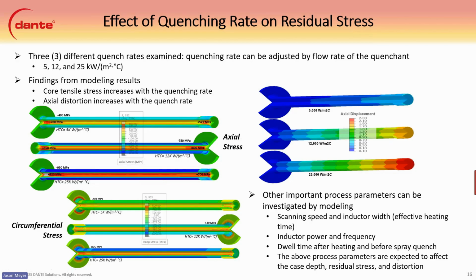Other important processes that can be investigated that we didn't do for this study were the scanning speed of the inductor and the inductor width. So effective heating time, so the larger heating region or the speed at which the inductor moves. The power and frequency, so that the temperature can get up to, and then the depth of the inductor. We can adjust that as well and see the results of material response. The dwell time could have a good effect before the spray quench. And then all these parameters are expected to affect the case depth, residual stress, and distortion of this part.